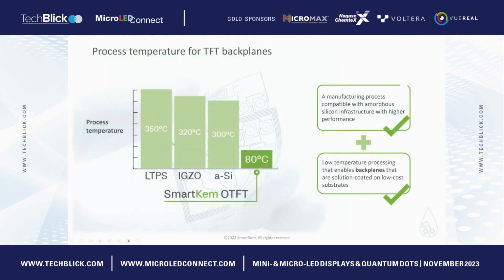So the key feature of our materials is that the semiconductors themselves are designed in the chemistry, and so the properties are determined by the chemical structure and not by any post-processing. The heating processes that are used are mainly just to evaporate the carrier solvent used to coat the liquid. So they can be processed at very low temperatures, and we've even done down to 80 degrees C for the whole process, and shown very similar performance of the devices versus the slightly higher temperature of maybe 120 or so as our standard process flow.